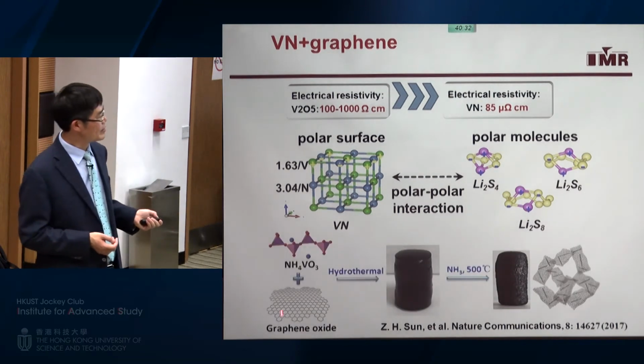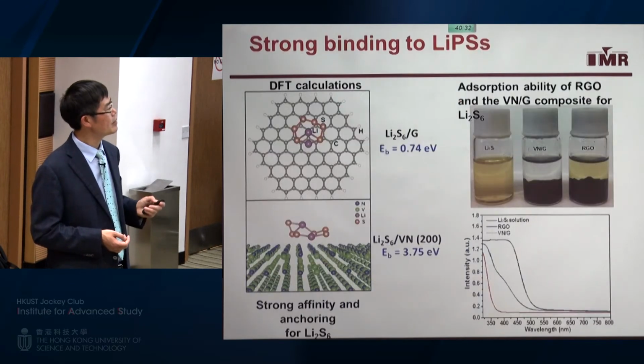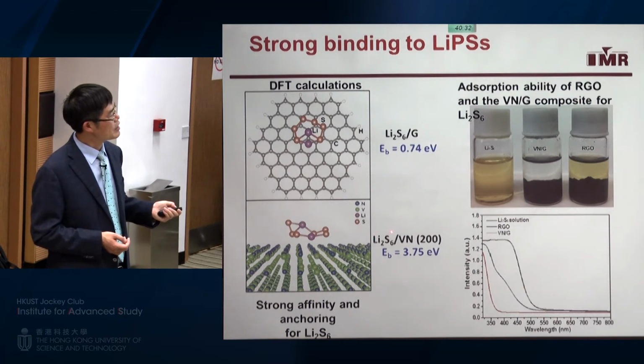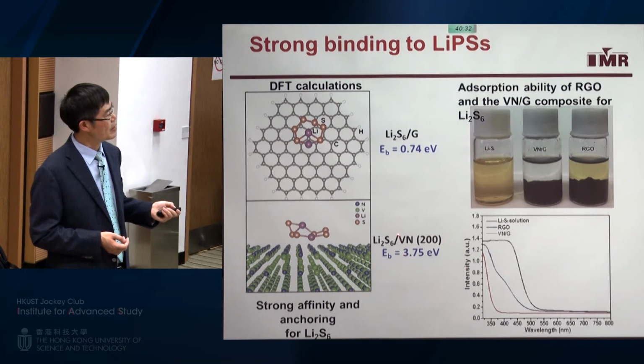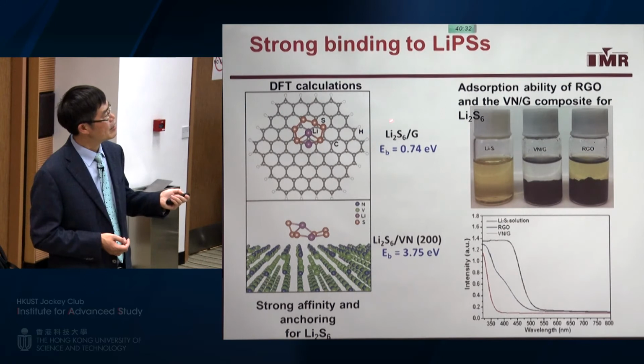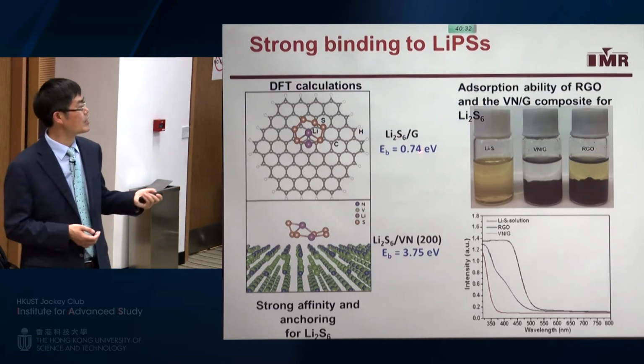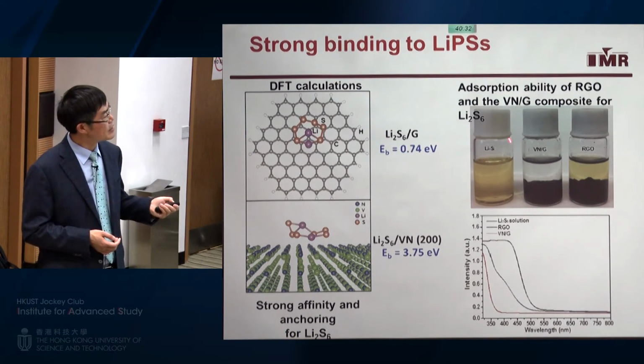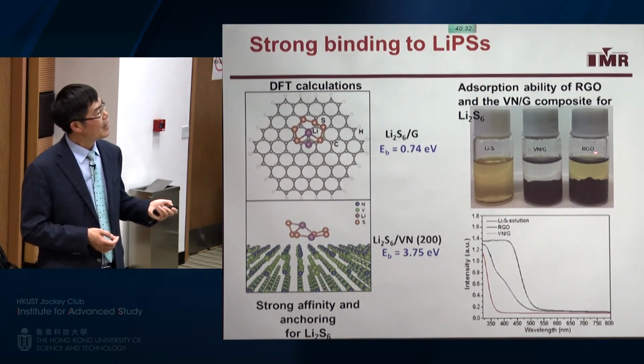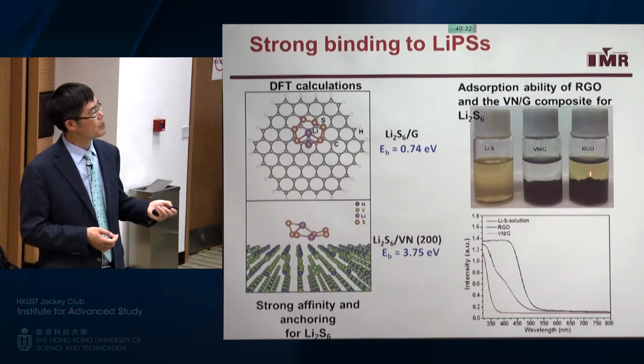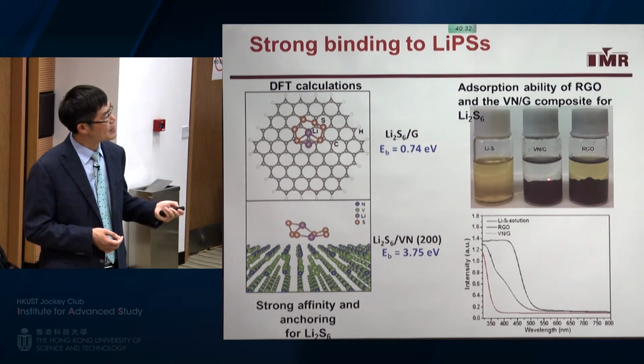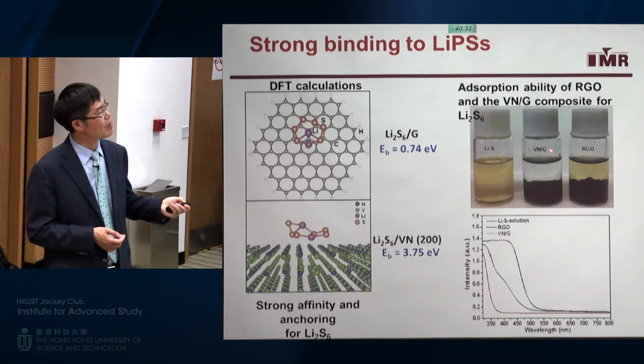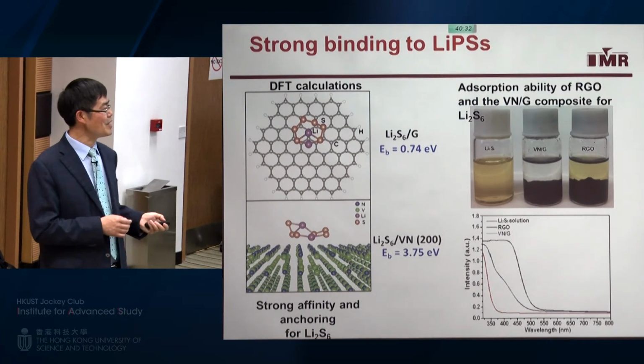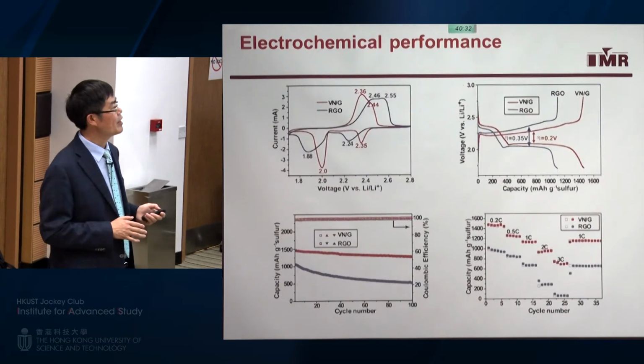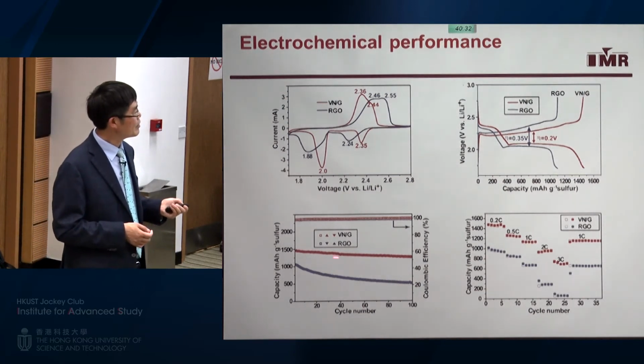So then we can incorporate this material on a 3-dimensional graphene structure. And then we found that this lithium polysulfide has very strong interaction with those metal nitrides, much higher than between lithium polysulfide and graphene material, which is only 0.74. For this experiment, you can see this lithium polysulfide solution, yellow color, is difficult to be trapped by the reduced graphene oxide with many oxygen functional groups. But it's easily trapped by the metal nitride, the graphene 3-dimensional structure. So that means we can use this kind of structure to trap lithium polysulfide.